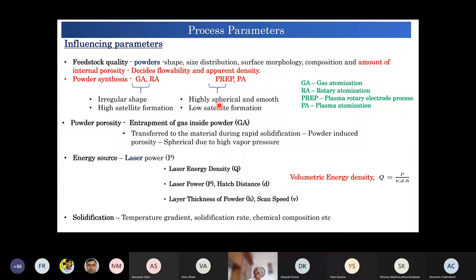We can't afford to have pores or holes, because they will lead to some kind of crack in due course of service. Now the shape and size distributions are important, because for all powder bed processes we need a fully dense packing, and there has been enough research done as far as the densification by packing is concerned. There has to be a size distribution. It has to be a Gaussian size distribution, a kind of thing where the packing density is decided by the size, the gradation in size.